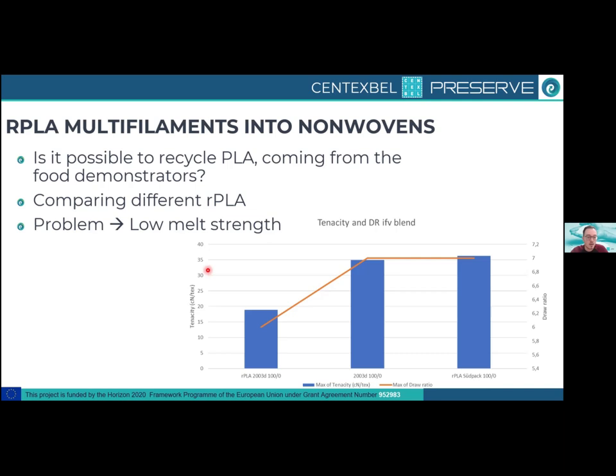On the other hand, we also have tried to look at different types of PLA, different types of recycled PLA, and compare them to conventional PLA. This is still somewhat ongoing as well, but we have some RPLA from Südpack that has really good mechanical properties already compared to some conventional ones like the 2003D PLA. We also had some recycled ones, as you can see on the left, but they are far inferior compared to the virgin one. So we are working with this RPLA from Südpack, which is a film grade PLA.